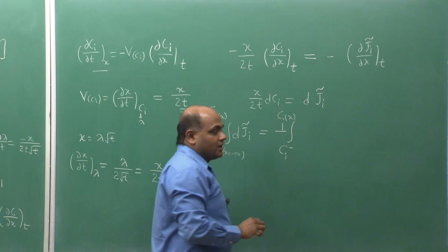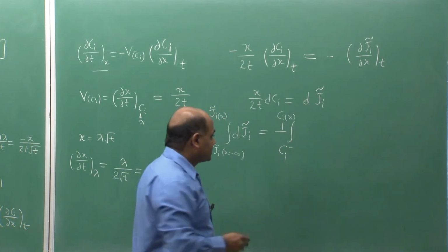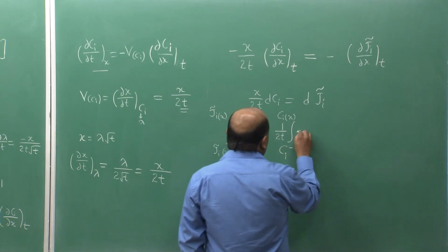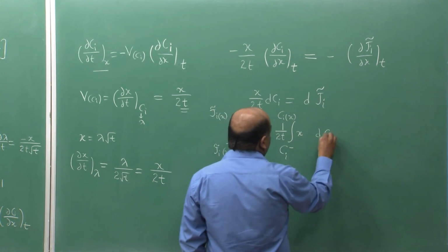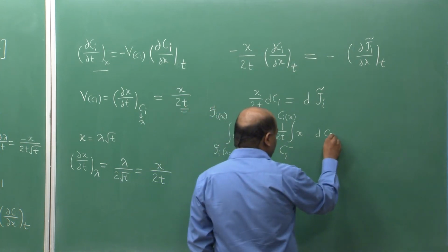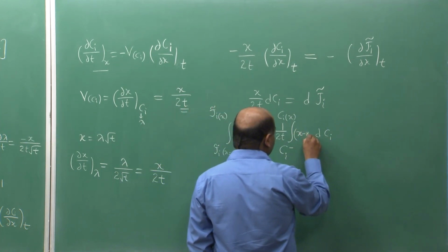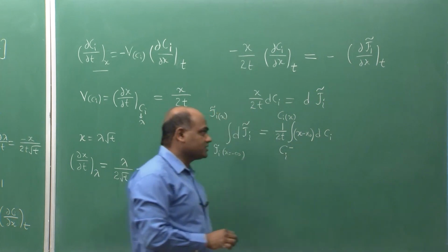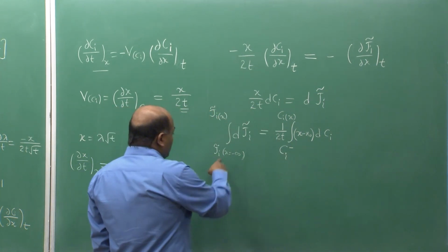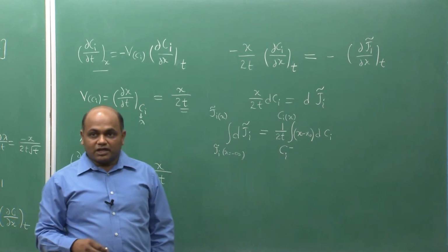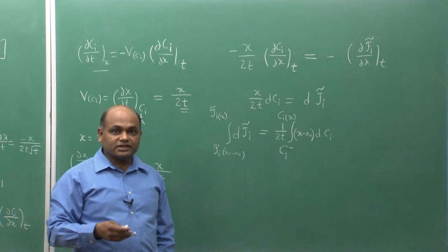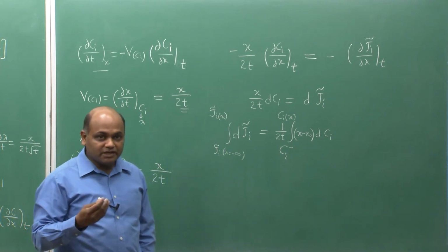and we are considering the fixed annealing time. So, we can take this t out here, x dCi, and more appropriately if we use x naught as our reference plane, this should be equal to x minus x naught dCi. Now, we know on the two terminals the diffusions will never penetrate, and so the fluxes at the two terminals would be 0.